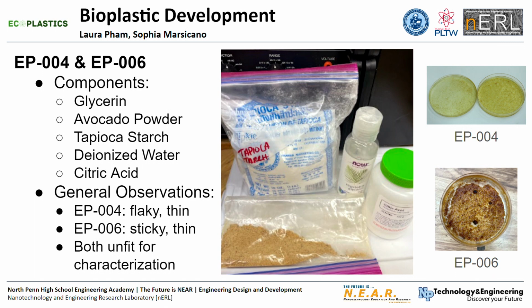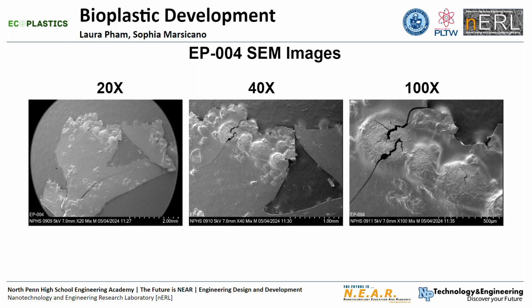EPO4 and EPO6 contain the exact same components: glycerin, avocado powder, tapioca starch, deionized water, and citric acid. However, EPO6 had half the amount of deionized water and slightly more tapioca starch. These adjustments did not change the resulting plastic anyhow, because both plastics were unfit for characterization. They both were not removed from the mold and didn't gel up during production like our last samples did. And as you can see in these SEM images, EPO4 was extremely flaky and paper thin, not ideal for a plastic.